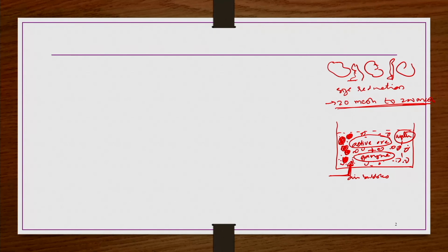Then the average density of this bubble is going to change. Initially there was only the air density. Now onto this bubble surface, solids, the active ores, are being attached, so the average density is going to be different. The average density of the bubble with attached solid is lower than the density of water in general. Because of that, these bubbles will rise up to the interface, and when they rise, they carry the particles attached onto the surface. These bubbles are taken out as overflow.